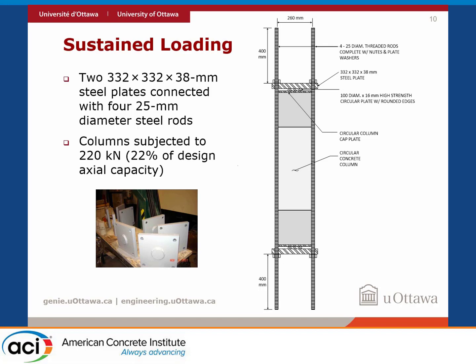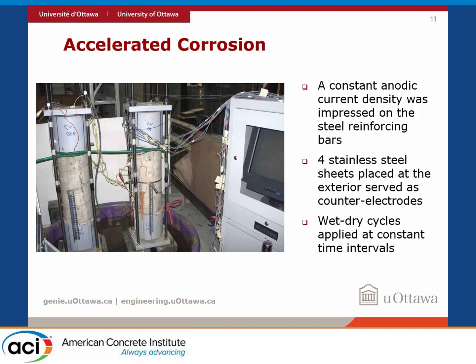Now, the steel rods were subjected to 55 kilonewtons tensile force. This was monitored throughout the entire process, and this amounted to 220 kilonewtons sustained axial compression, which represents around 20% of the design capacity of the columns. While they were sustaining load, they were subjected to an accelerated corrosion regime, so the longitudinal or spiral reinforcement, depending on what type of columns we were corroding, had a constant anodic current applied. The current density that we targeted was around 250 to 300 microamps per centimeter square. We had to place stainless steel sheets outside the columns. You can see them around here.